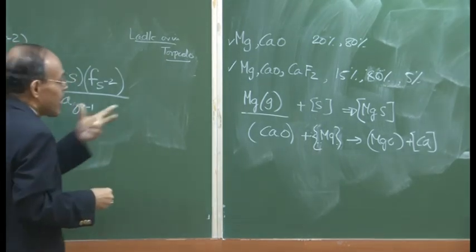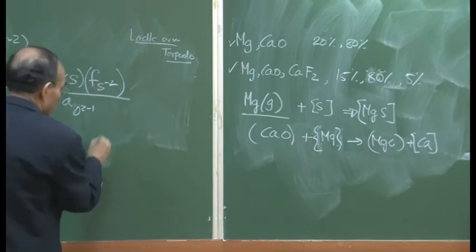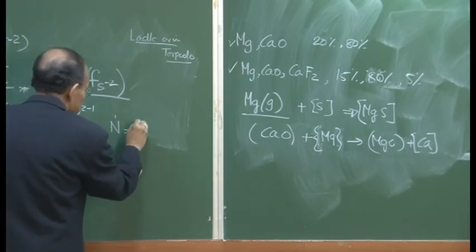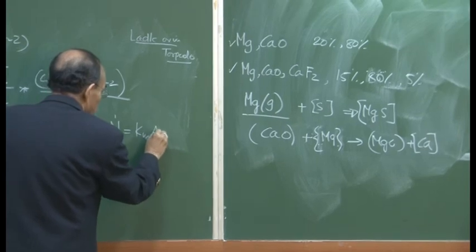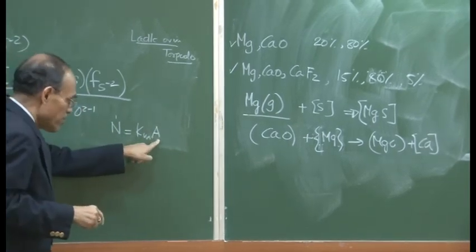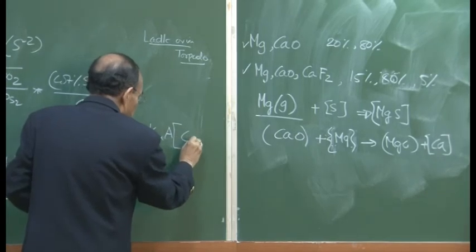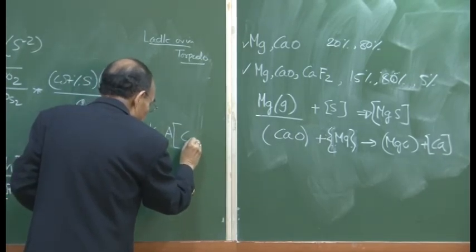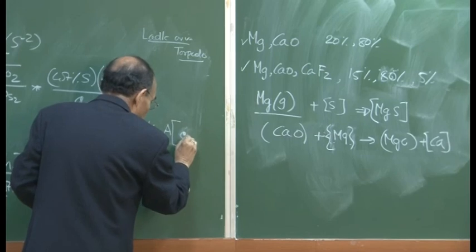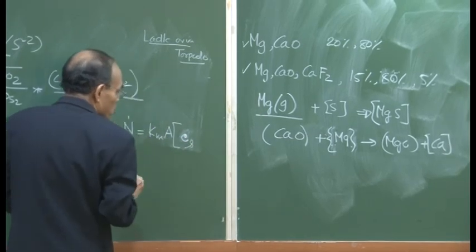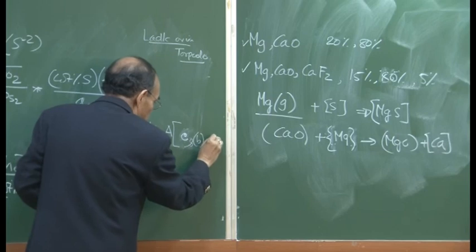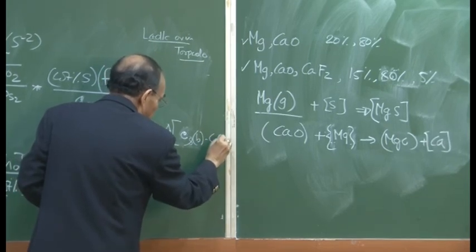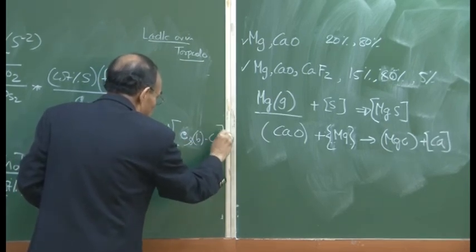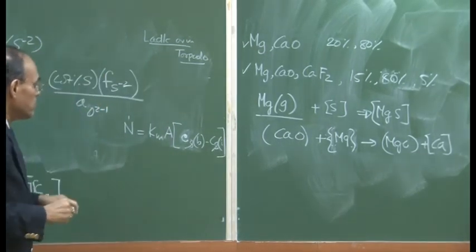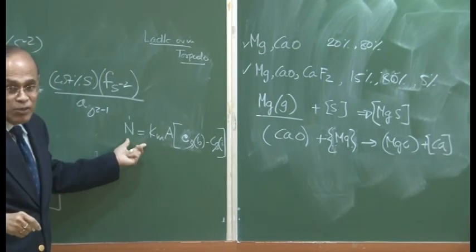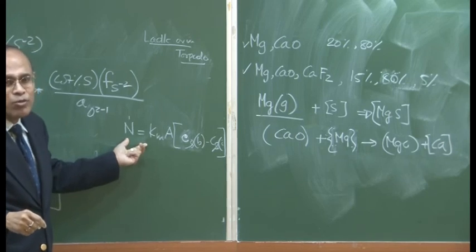That will be known to us if we consider the kinetics of the slag metal reaction. And we know that the slag metal reactions are first order reactions, and the first order reactions basically tell us that the rate of transport is equal to the mass transfer coefficient times area times the sulfur concentration. So I would write small c, not sulfide capacity. This is the sulfur concentration in the bulk minus the sulfur concentration in the interface. Because when you say that desulfurization is mass transfer controlled, basically it is a melt phase transport process.